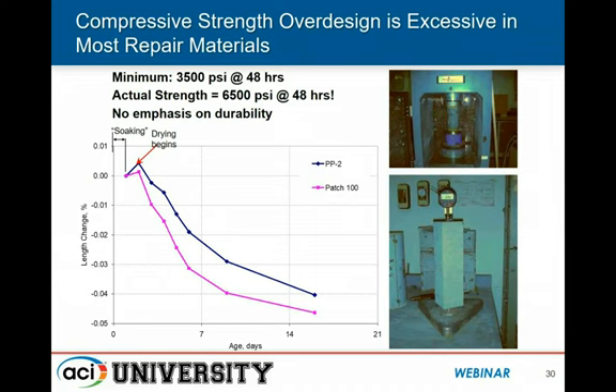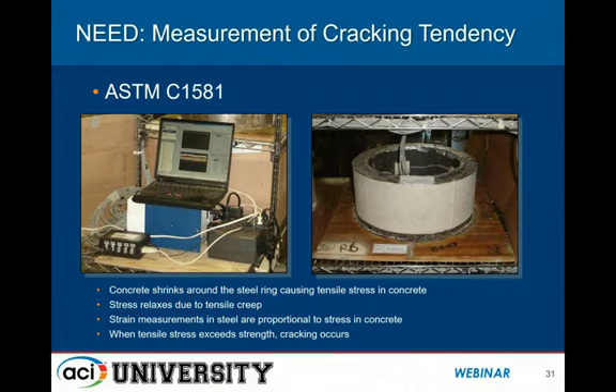What we often see with some of these mixtures is, again, the length change testing doesn't really indicate a whole lot of a problem here. I mean, the early age length change is higher than we want it to be. The strengths were nearly double what was needed in some cases with the prescriptive mixes. So no emphasis at all given on durability. And we wanted to get away from that because, again, the ring shrinkage test is available. It allows engineers to develop specifications that prevent cracking problems.